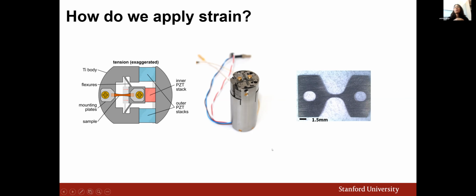And particularly for the work that I'm going to be talking about today, while we're moving into trying to apply strains to more layered quasi 2D materials, rather than mounting the sample directly into the jaws of the cell, as is shown in this schematic, we're actually going to mount the sample onto the substrate shown here in this neck region of the substrate, which is going to allow us to more reproducibly and robustly strain our sample through repeated strain cycles, while maintaining the crystallinity of the sample that you need to perform X-ray measurements.